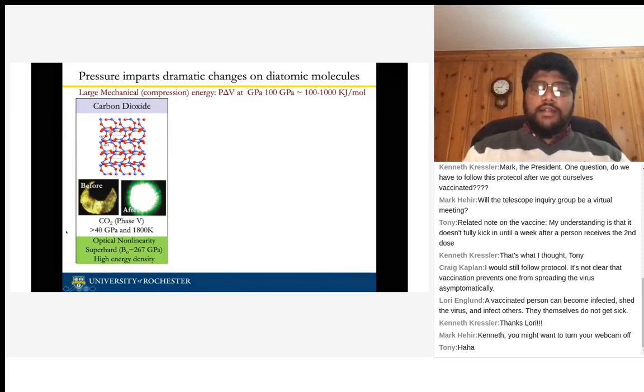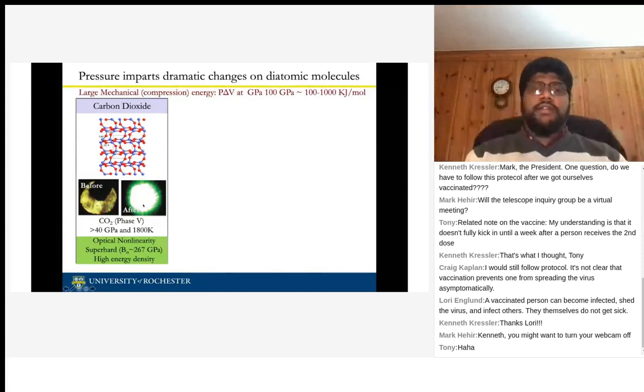So this is what the picture shows you, that this is the sample. And then you shine the IR laser, and you see a lot of green light coming out. It's optically nonlinear. And this is also a very high energy density material. So out of a greenhouse gas, you make a new material which has totally different properties.